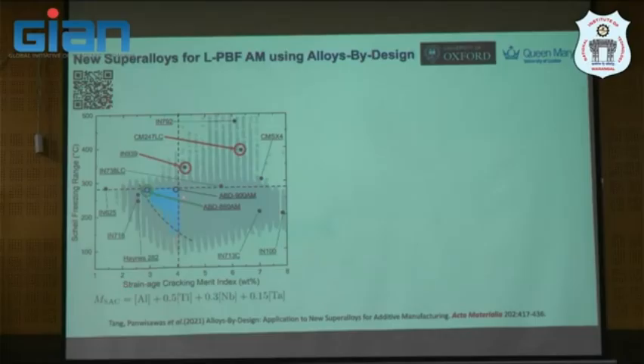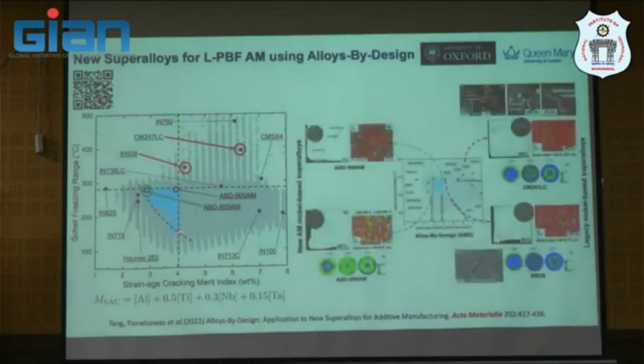So one is actually very minimum in crack, based on this index, and another one a little bit acceptable or at the border. So that's what we call ABD 850, which performs well at 850 degrees centigrade, and 900 degrees centigrade. So we call it ABD 900.